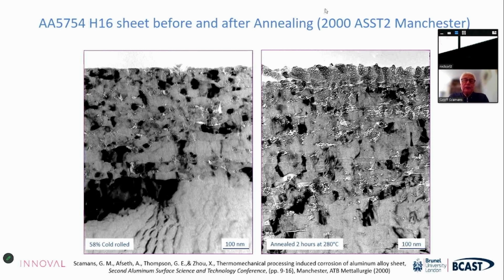absolutely true. If you look at the left-hand image, you can see what the near surface layers of this alloy look like, and the difference between the near surface layers and the underlying microstructure. The surface is characterized by, in this case, a fairly uniform layer of ultrafine, about 100 nanometer diameter grains. When we anneal, we get more oxidation, but the grains are stable because they're pinned by the oxides at the grain boundaries. You can see there's more oxidation on the surface.